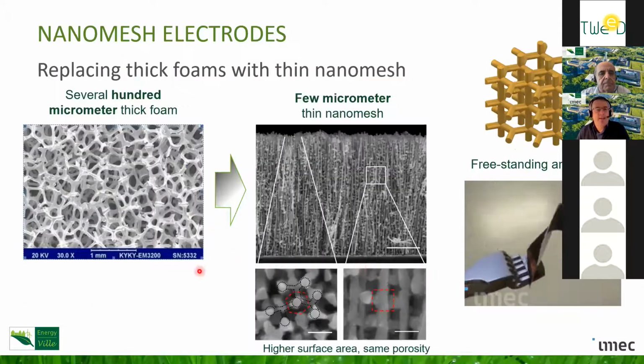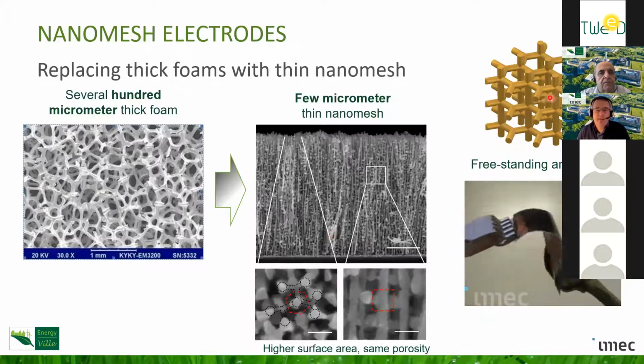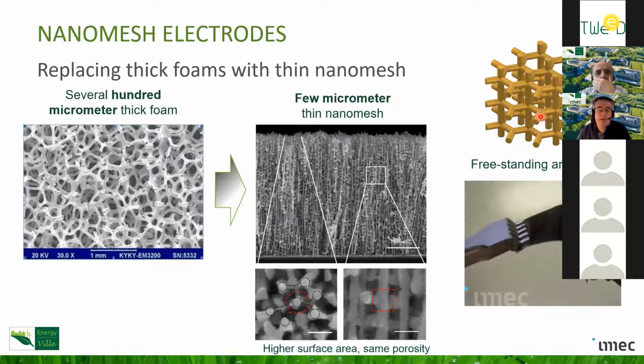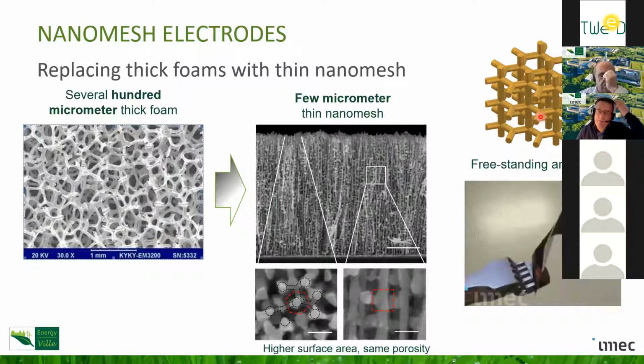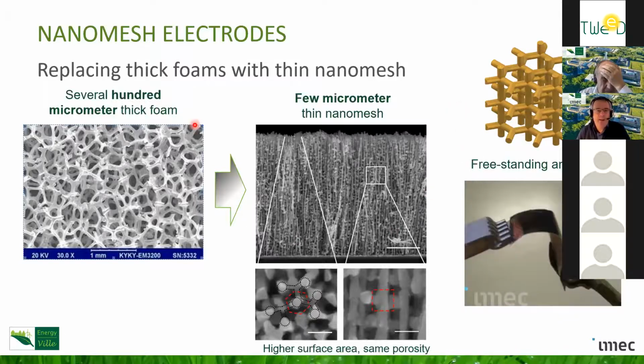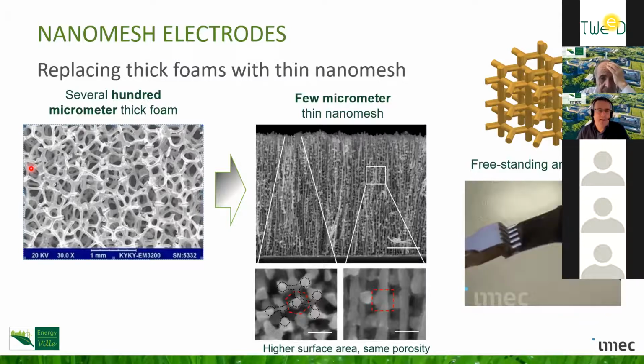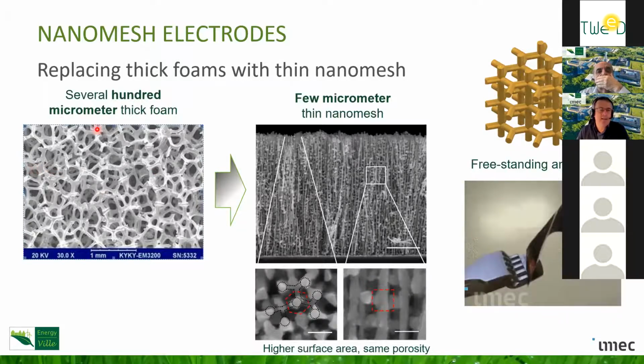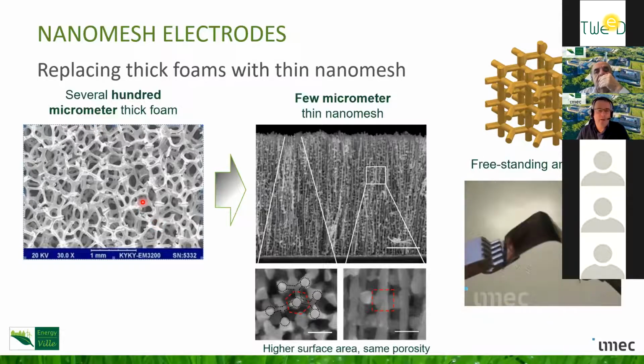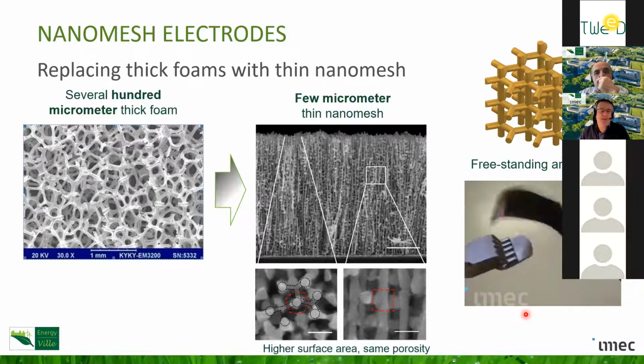And as mentioned, the key element is this nanomesh structure, where you see a schematic here. It's the same kind of structure as used for batteries, but activated in another way. Typically, existing structures use this type of thick foam, which has a highly porous structure. But we use this microstructure, thin nanomesh, which is much smaller and has a very high surface area for the same porosity, and it's a very regular structure, and it can be made very thin. Actually, you can make it bendable even if needed. It's freestanding and it's flexible.